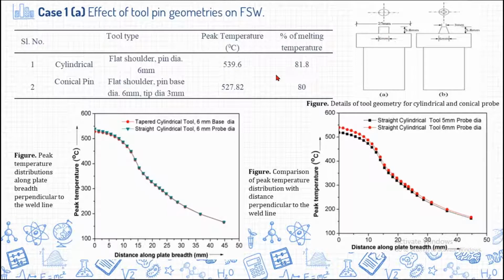We considered these two geometries for generation of heat, keeping properties like rotation speed and welding speed constant, and we observed the peak temperature distribution for the straight cylinder tool and the taper cylinder tool around 540 and 545 degrees centigrade. Both tools give very close peak temperature, keeping all other parameters constant. This is the effect of tool pin geometry, tool pin shape, on temperature.